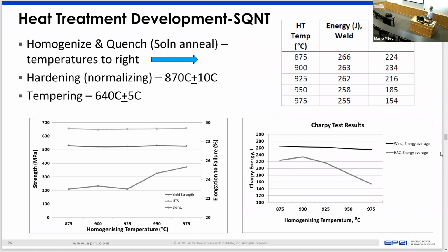We've done a lot of heat treatment work to understand those. And essentially we've arrived at working at 875C, still providing good properties. You can see the trail off here, but we're showing good properties in terms of toughness at around 875C heat treatment. That heat treatment involves a homogenization, a quench, followed by a hardening or a normalization of the material, another quench, and then a temper. So it's reasonably complex. You got to think about this again in large sections that we're working with. How do you heat treat those without distorting them?